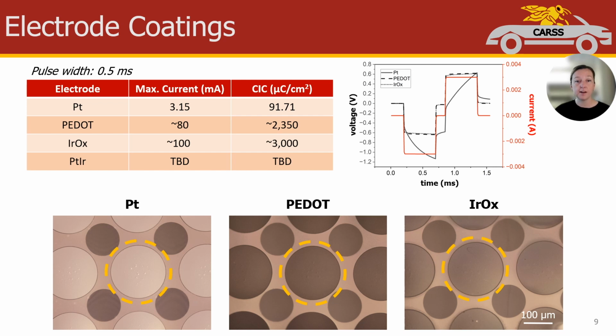So far, we have tested both PEDOT and iridium oxide, both of which provide a 20 to 30 times increase in CIC compared to platinum. We've only tested current injection of up to 30 milliamps due to limitations of our test equipment, but we anticipate maximum allowable currents of approximately 80 and 100 milliamps for these coatings based on the linear relationship between CIC and the interphase potential in the voltage transient measurement. These coatings can be seen under optical microscope, as shown in the images across the bottom. The dotted yellow line is encircling an exposed microelectrode, which appears darker in the right two images after coatings have been applied. We are also in the process of testing platinum iridium coatings, but do not yet have that data available.